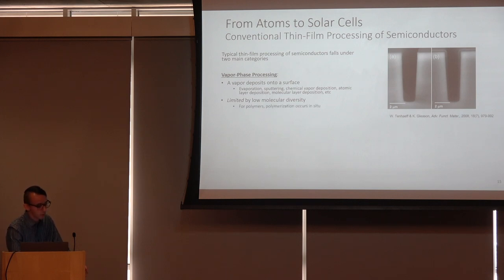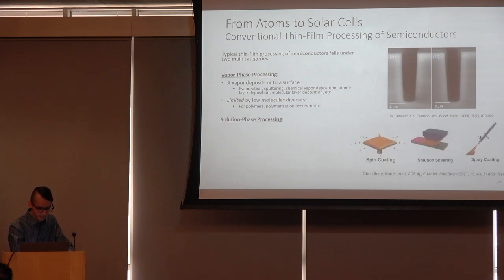But you're limited by low molecular diversity, and this is due to the fact that, particularly for polymers, you're polymerizing in situ, which means that perhaps your monomers require heterogeneous synthesis, at an interface between liquid and a solid, so you can't necessarily produce those monomers from the vapor phase. And additionally, the bigger your monomer, the lower your vapor pressure, and so you can get to a point where you just straight up can't deposit many materials by these vapor phase techniques.